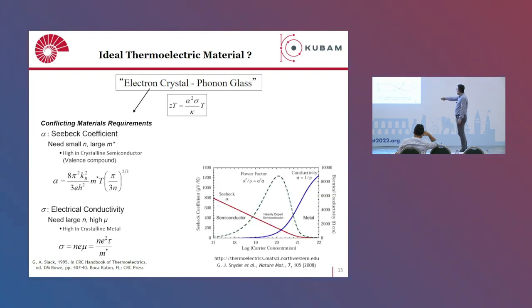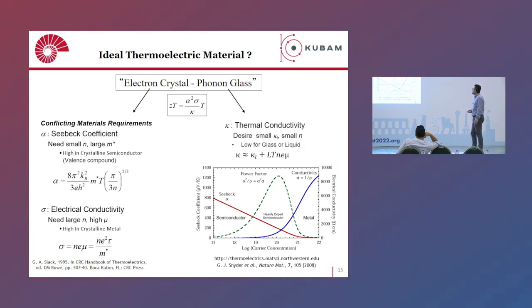So here you can see that the power factor, which is the multiplication of the square of the Seebeck coefficient times the electrical conductivity, is maximized for basically the carrier concentrations within this window. So let's say 10 to the 19 to 10 to the 21 per centimeter cube of carriers. And this is valid for the heavily doped semiconductors. So you should tune the carrier concentration in a sense to tune the electronic properties.